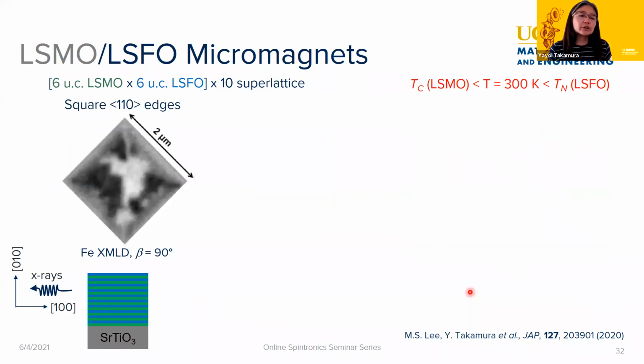And then again, what we did is look at different shapes. So this is your diamond, or the ones where we've rotated them. Now the edges are along nominally the hard direction for this antiferromagnetic material. And so now what you can see is that there are very sharp contrasts in the center.